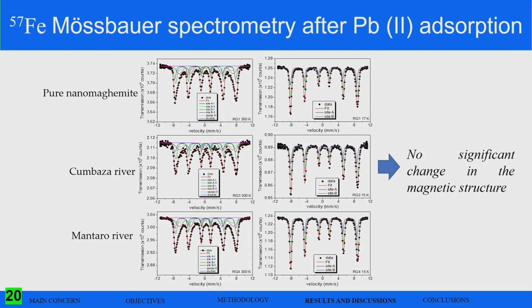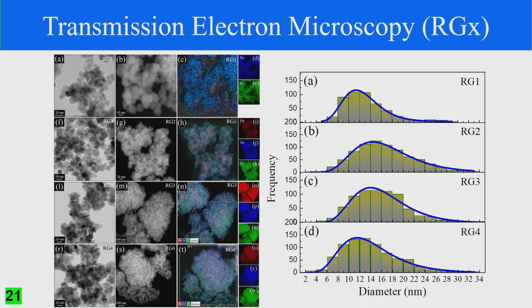Of course, when we apply these nanoparticles as adsorbent and we remove lead from water, we can also obtain the Mossbauer spectrum, and we do not see a significant change in the magnetic structure, as we proved from the Cumbaza and Mantaro rivers. How we know that we have lead on the surface is because we performed X-ray photoelectron spectroscopy, but due to time, I will not show that.